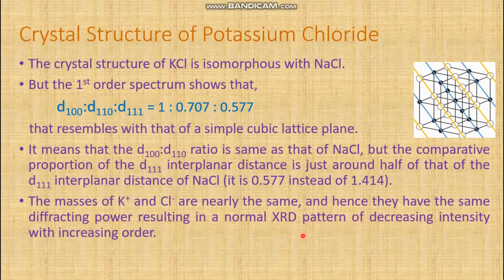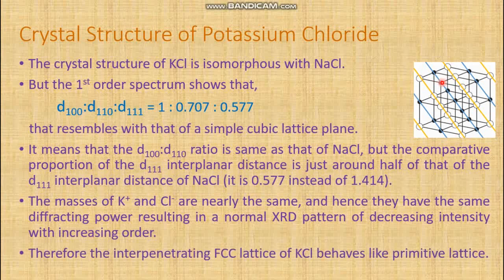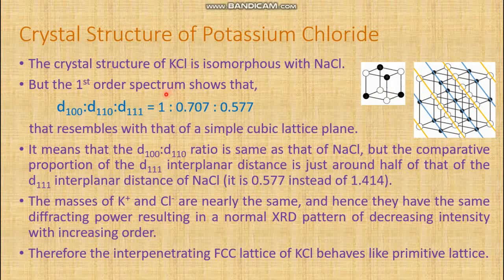In KCl, unlike NaCl, the intensity decreases as the order increases for all planes including 111, because both lattice points are equivalent in electron density. As a result, the two interpenetrating FCC lattices of KCl behave like a single primitive lattice. If you take one-eighth of the overall unit cell, it appears like a primitive lattice — which is why the ratio 1 : 0.707 : 0.577 (simple cubic) was obtained for KCl. That concludes this topic. Thank you and have a nice day.